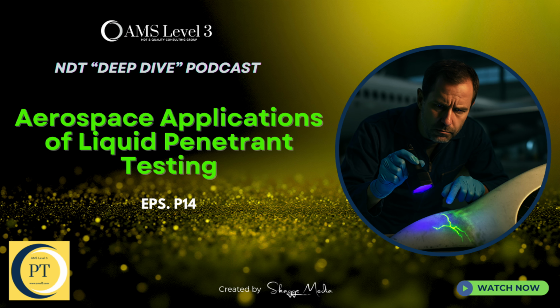They used a technique called sensitivity tuning. Instead of using a single off-the-shelf product, they mixed a family of compatible penetrants, an ultra-high sensitivity component with a lower sensitivity one. And by controlling that ratio, they could achieve a custom intermediate sensitivity, like a 2.5. Why customize it? Why not just use the highest available sensitivity?